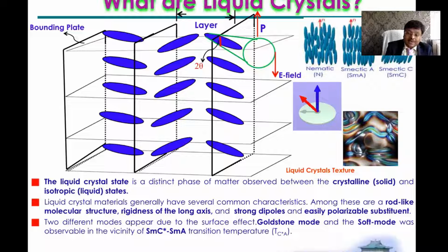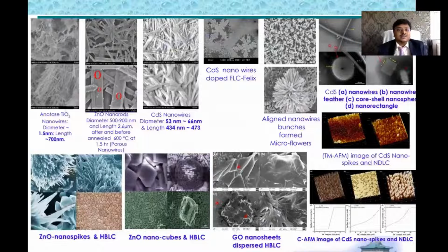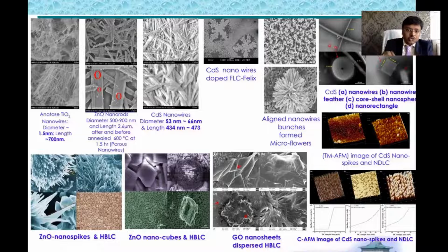And there are several phases. Let's say nematic, smectic C, and smectic A. With temperature, it gradually changes. So it's a very interesting thing. So this is our experimental confirmation of our different kinds of morphology, like TiO2. We started with TiO2, zinc oxide nanorods, CdS, and you can see the different starting materials we used, different shapes and morphology. And after that, when we disperse CdS into liquid crystals, a microflower-like structure evolved.